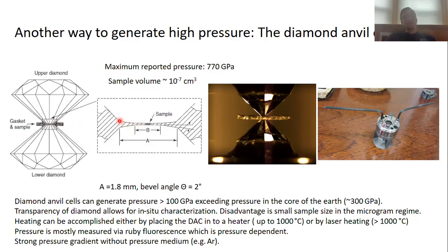And you choose these bevels in order to minimize the forces that act on the corners here, which can actually make your diamond break. So actually you enhance the lifetime and the pressure range that you can reach for your diamonds.